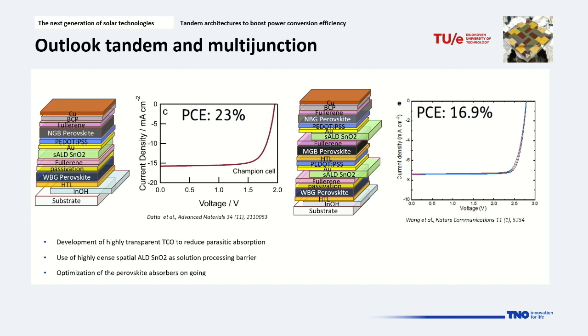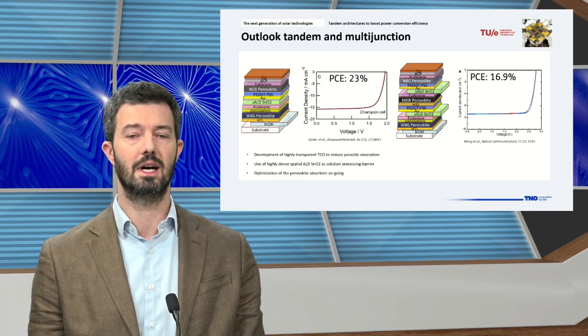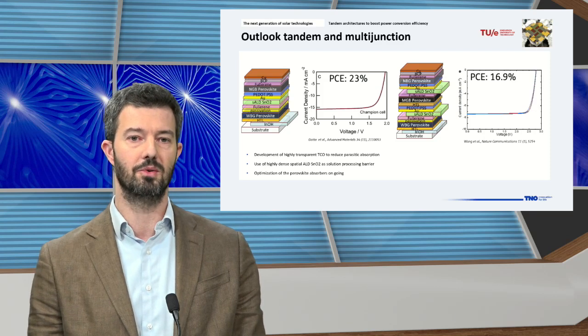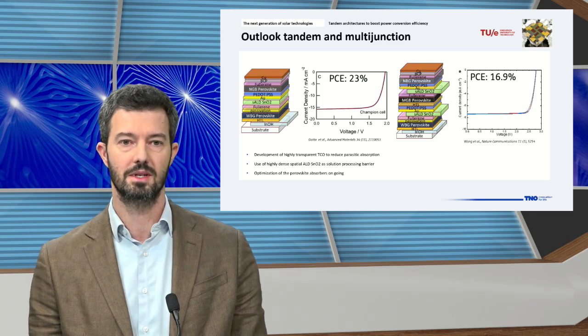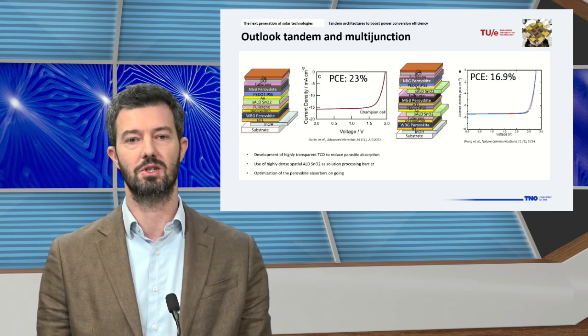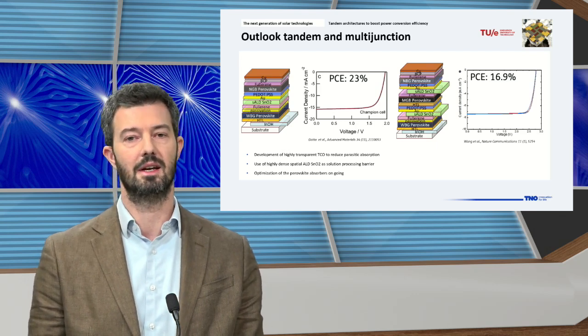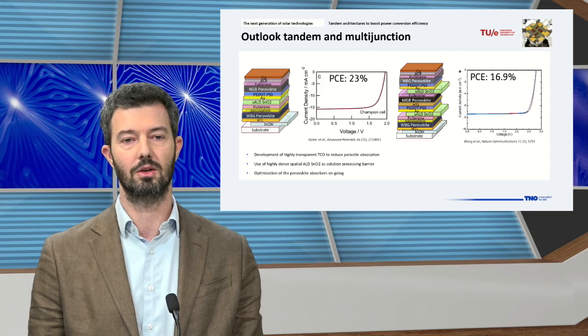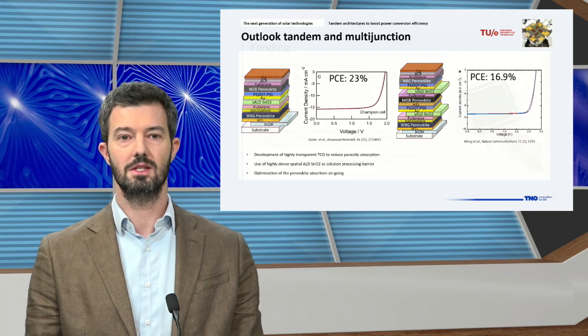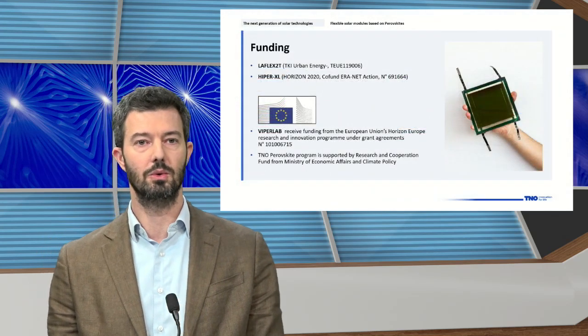In this case, we were, I think, one of the first in Europe to demonstrate a high-efficiency triple junction device, with an efficiency at that time, 3 or 4 years ago, of 17%. We achieved this because we can provide very highly transparent TCOs and highly dense tin dioxide layers that are really required for this type of technology. And with this, I would like to conclude.